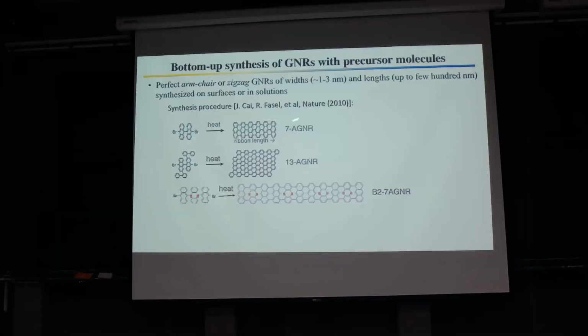And this technique is pioneered by Roman Fasel's group in Switzerland. So you take a molecule like this, you will get a 7 armchair graphene nanoribbon. 7 here refers to 7 rows of carbon atoms forming the width. And taking a bigger, different molecule, then you can form a 13 armchair graphene nanoribbon. And if you take a molecule with some dopants in it, here is a pair of boron atoms, then you can form a perfectly periodically doped graphene nanoribbon. And all this has been made already.